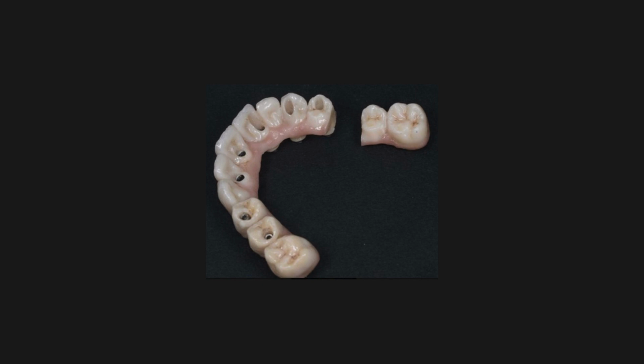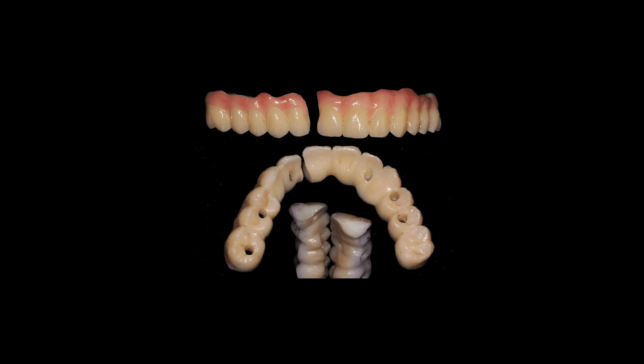1. Excessive heat during milling. Overheating zirconia during dry milling or poor cooling leads to internal stress and microcracks. These microcracks may be invisible, but they reduce long-term strength and increase the chance of fracture under functional loading.